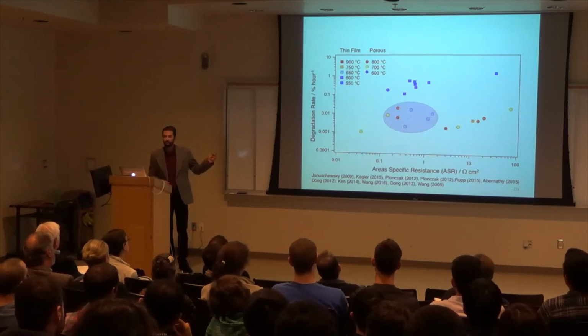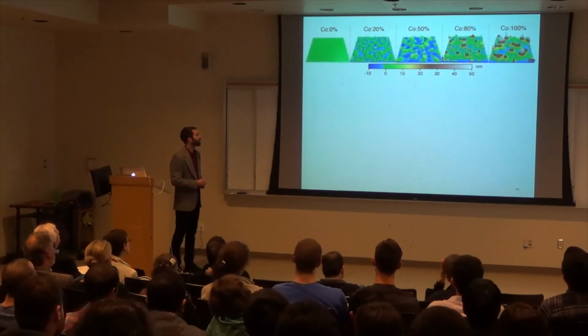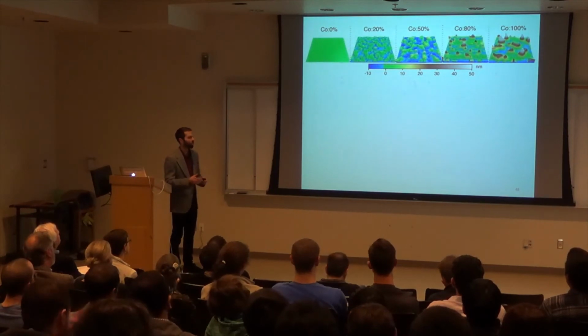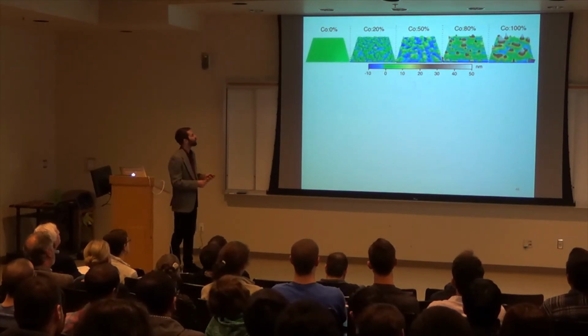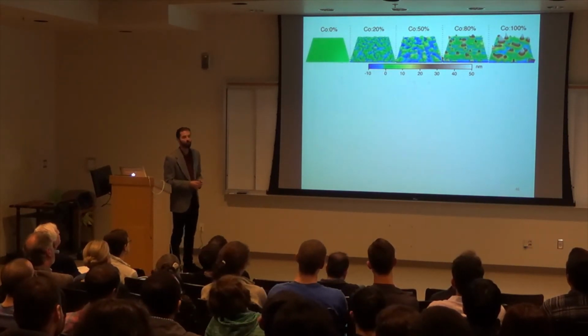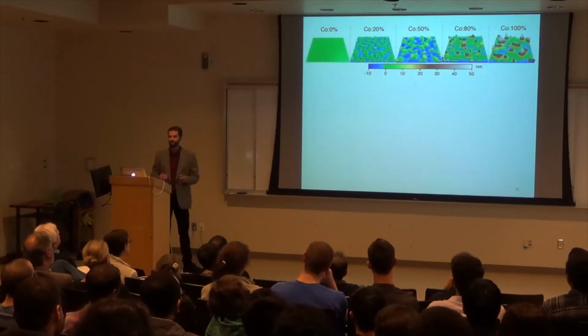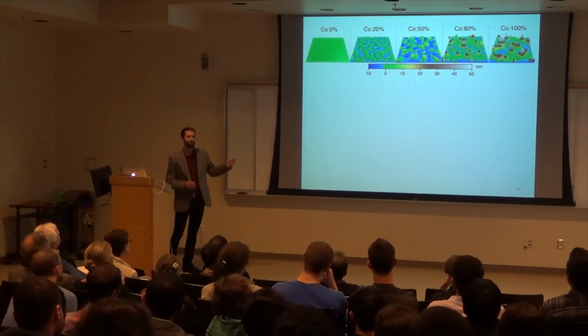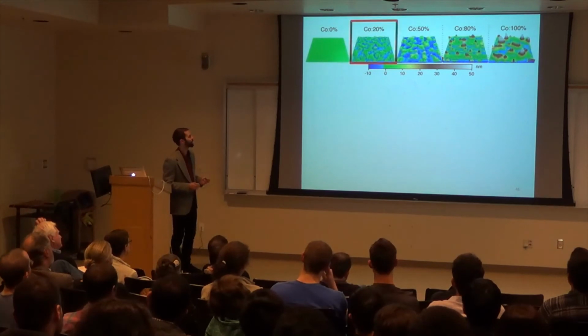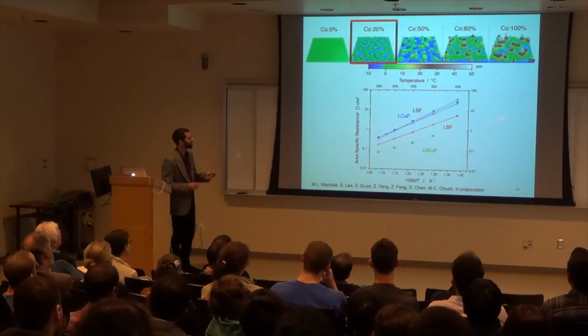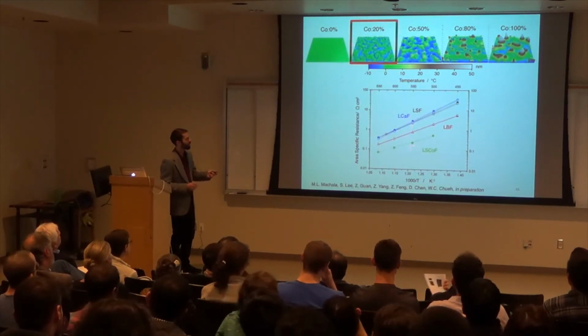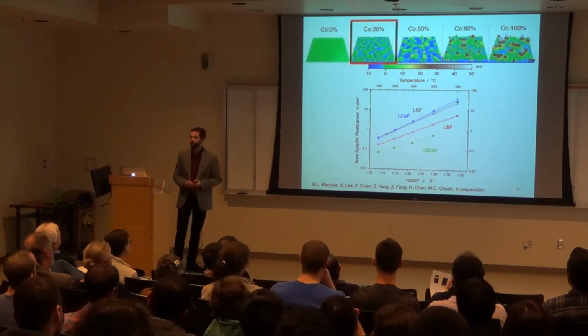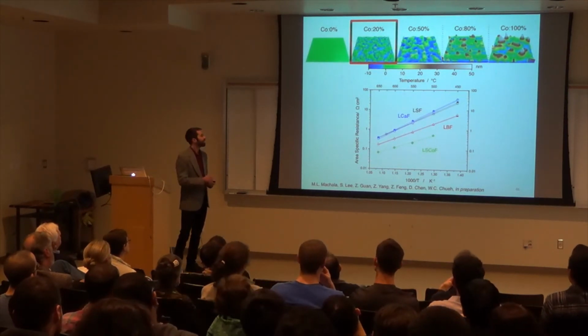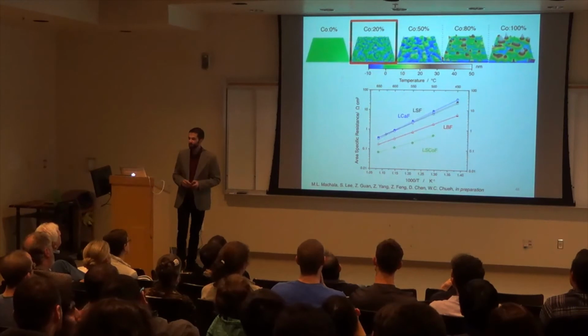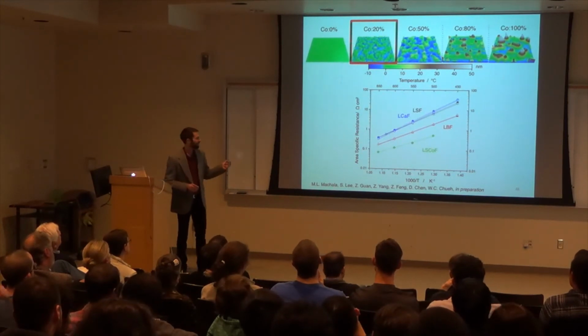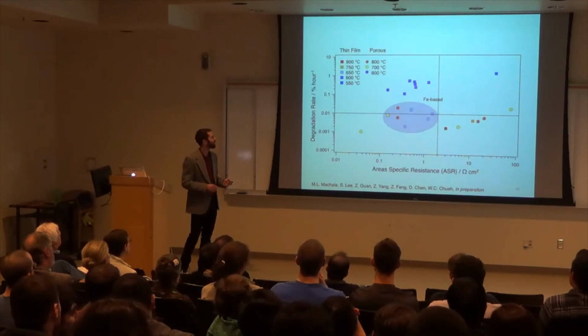And so to be a little bit more competitive with these materials, we turn to a sample that has a little bit more cobalt, 20%, not a whole lot. And when we put in just 20% of cobalt into this material system, we can see here, compared to what you've already seen, that the catalyst is performing much better than what we saw previously. And so when we put that on our figure of merit, we say, oh, it's a better catalyst, right?